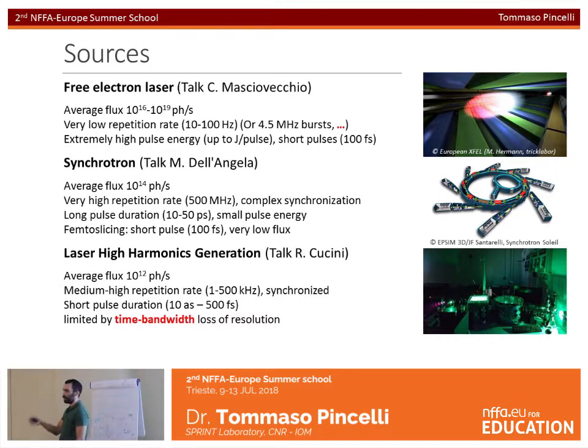There is one way to achieve high temporal resolution with a synchrotron, that is femtoslicing. So you send in a laser that selects only one part of the bunch, very narrow. So you can achieve hundreds of femtoseconds, but you have extremely low fluxes because you are bound by the repetition rate of the laser, so you can use only a few bunches of the synchrotron and only a part of the bunch. So you are throwing away an enormous amount of photons.